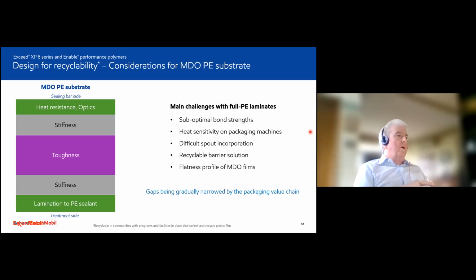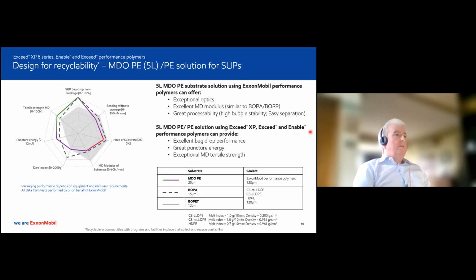Now, this is, as I said, a very oversimplified diagram. There will be different arrangements that people can use and blend, but these are the key aspects to it. And of course, lastly, you need to have a side to laminate to the PE sealant. Notice in this particular example, I haven't talked about including a barrier resin of any type. This is just a straight polyethylene type. So I'll give you an example now of a 5-layer MDO substrate structure where it's been laminated to a 5-layer PE sealant. And I'm going to compare that particular structure against a BOPA structure and a BOPET structure laminated to some competitive sealant structures.